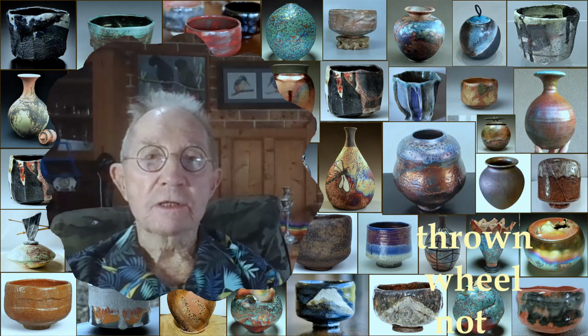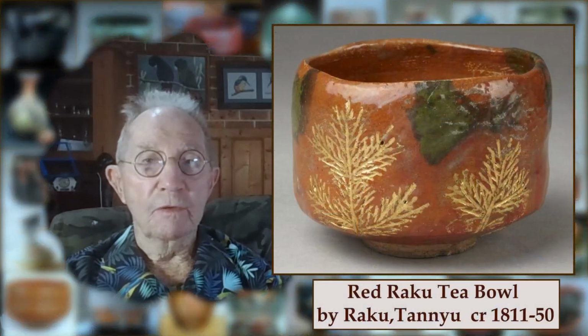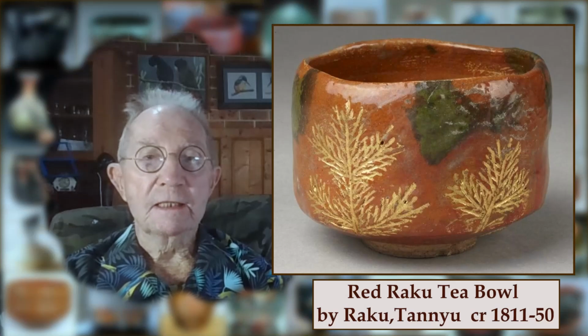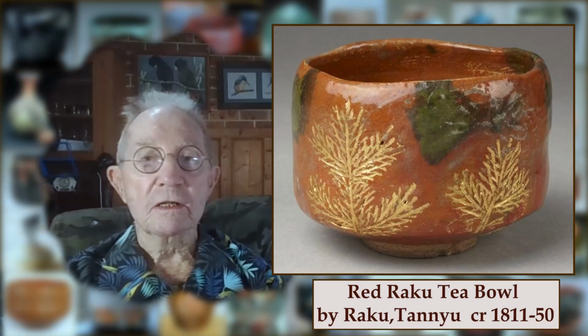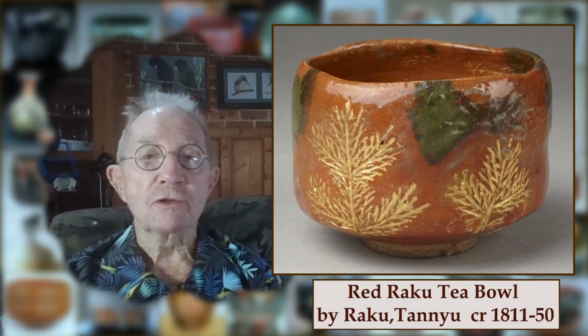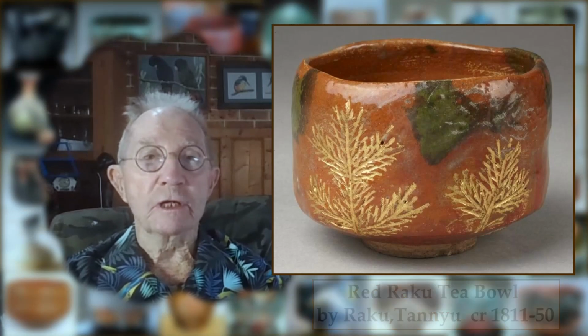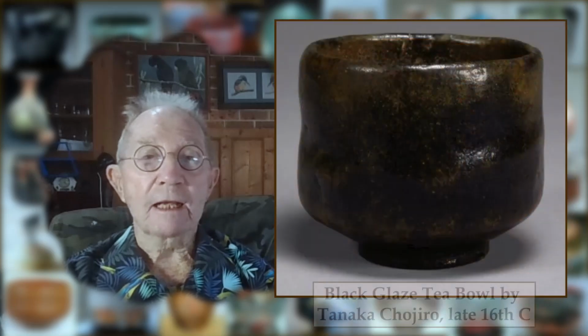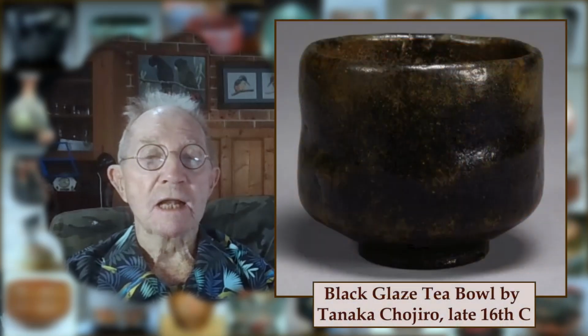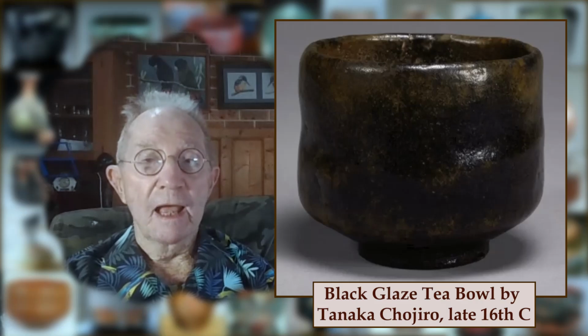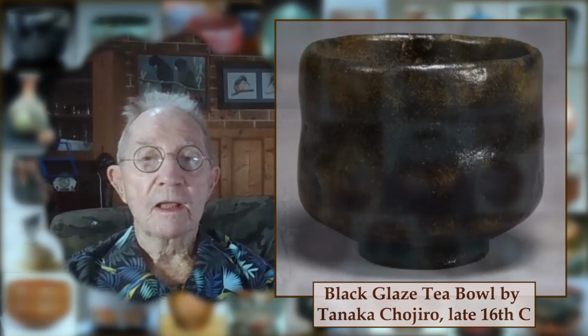There are two kinds of Japanese raku: red ware, which is glazed with lead glazes, low-fired and traditionally taken out of a red-hot kiln and allowed to cool naturally in the air or by putting it in water. And black raku, which is glazed with feldspathic glazes containing several metallic minerals, fired to stoneware temperatures and allowed to cool in the kiln.